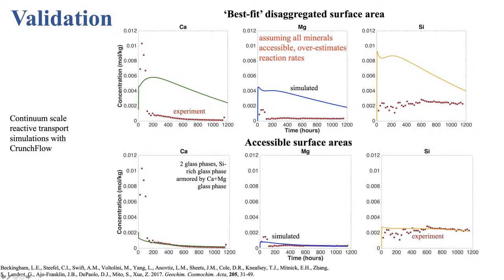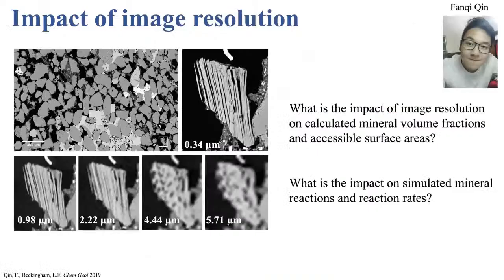But when we used our image obtained accessible surface area, we found we were able to successfully capture the reaction rates from the core flood experiment. So what we wanted to understand then is a little bit more about the imaging process. In particular, what resolution should we be collecting the images at?